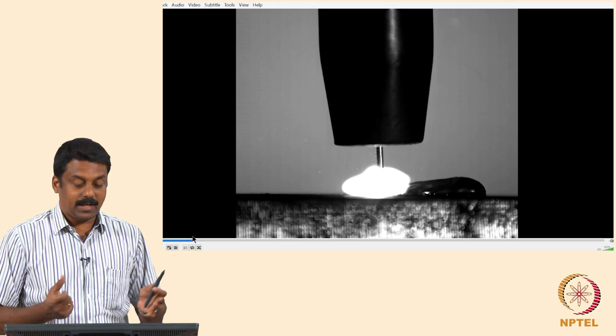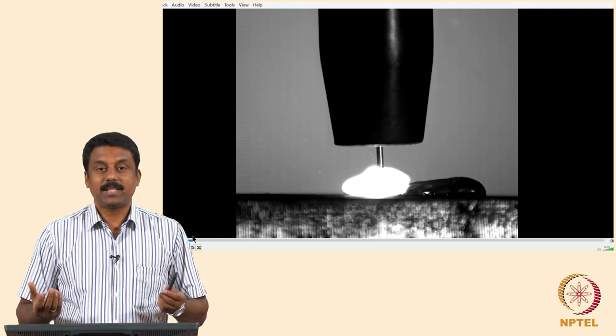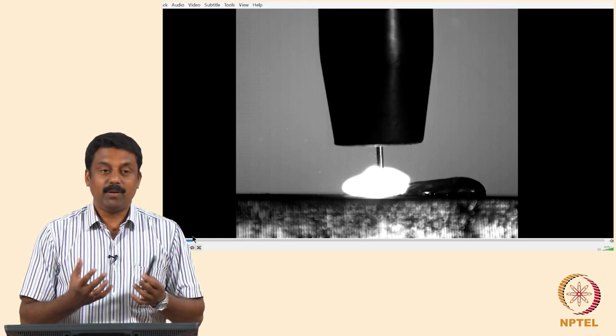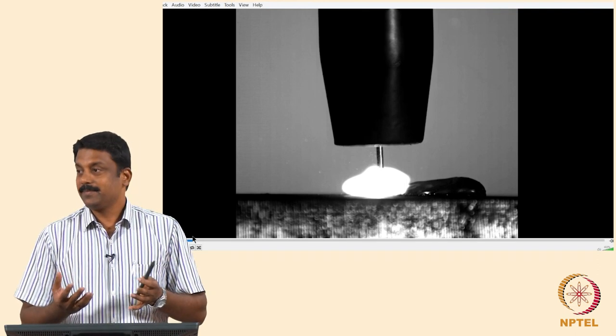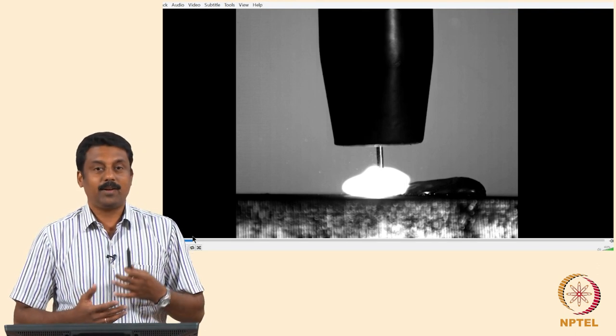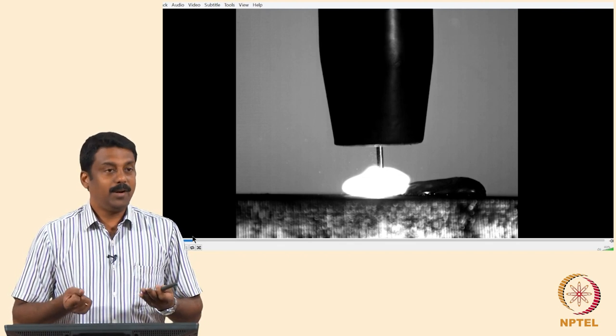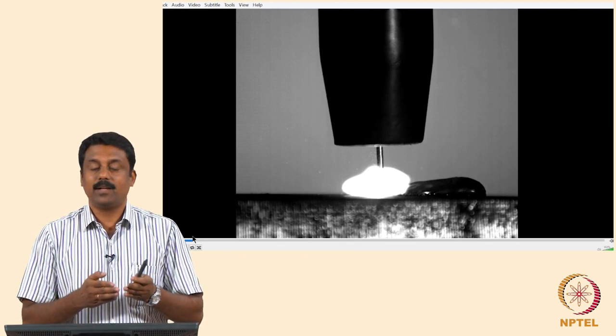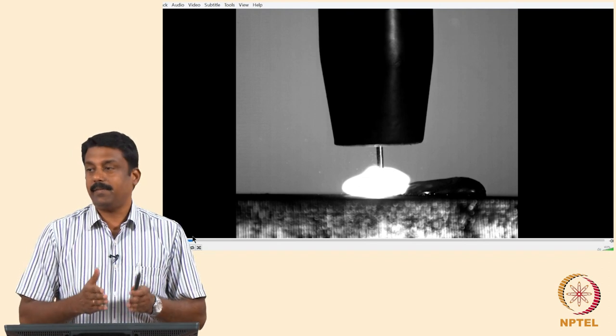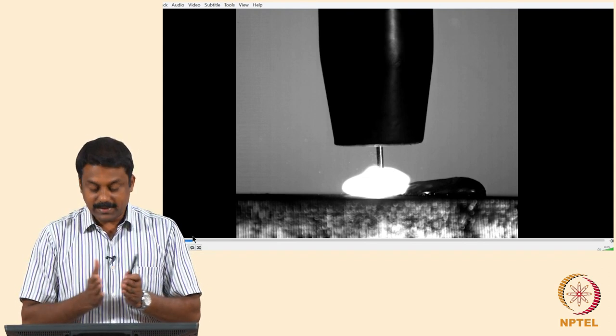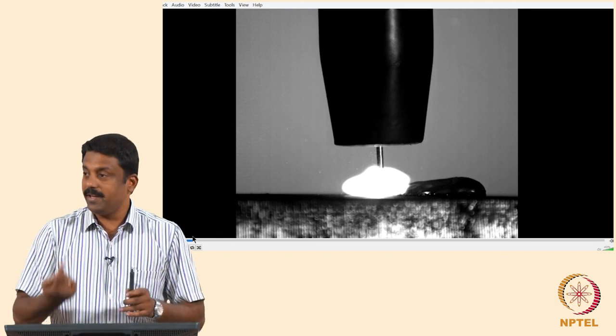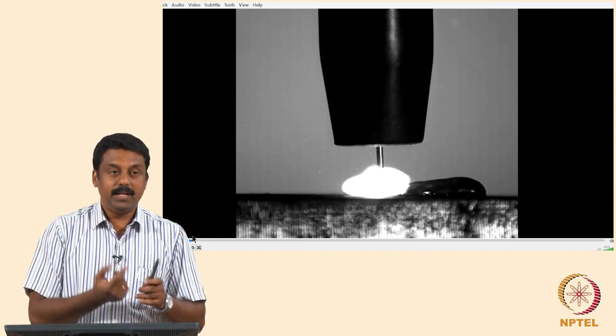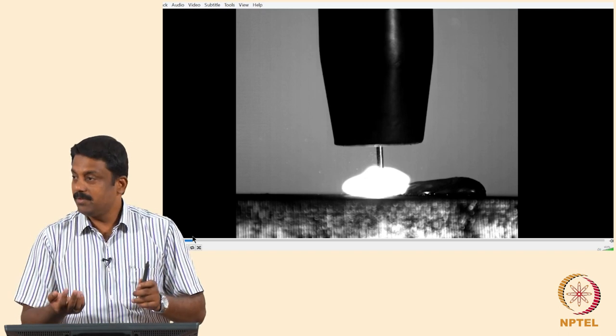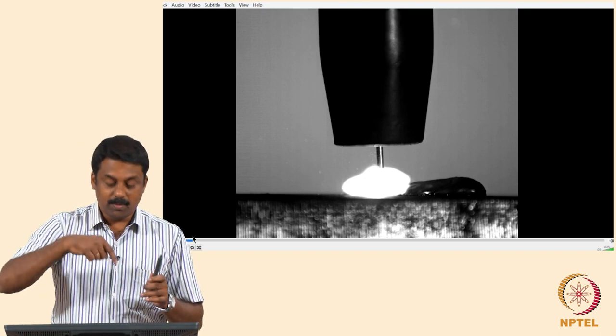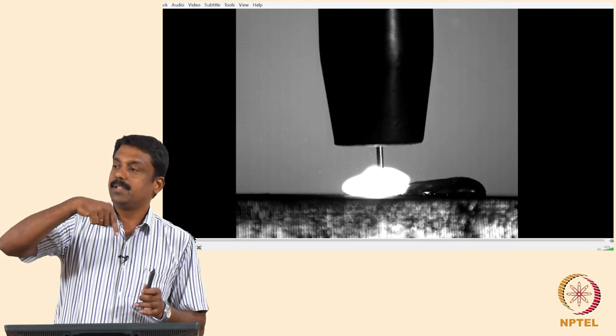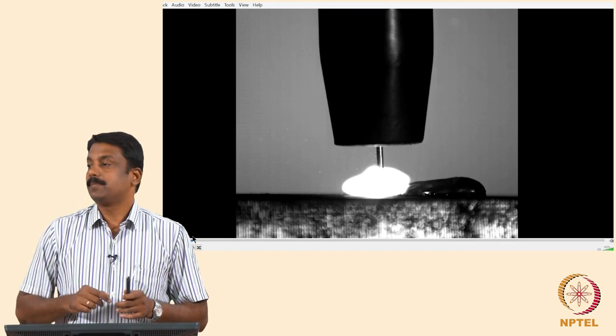So to achieve such a kind of complex metal transfer, the power source characteristics are extremely important, because the power source would also calculate how much it melts. The melting rate should be calculated accordingly, and the wire feed rate also controlled, so that you can establish the short circuiting at a given defined interval. The moment short circuiting is established, again the power source should measure the voltage of the system, and the moment the voltage becomes extremely small, the current should be switched off, and then the droplet can be detached by retracting the wire back.